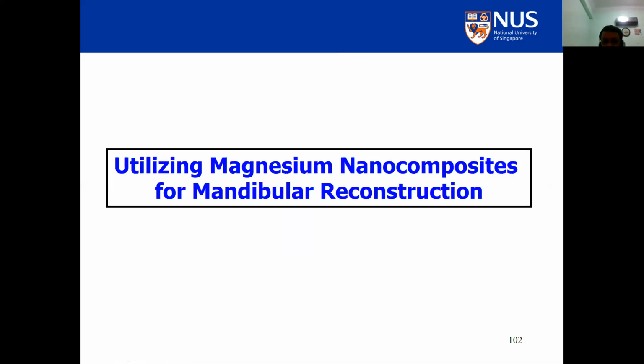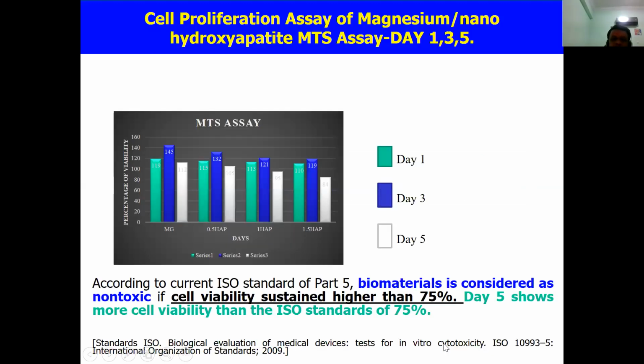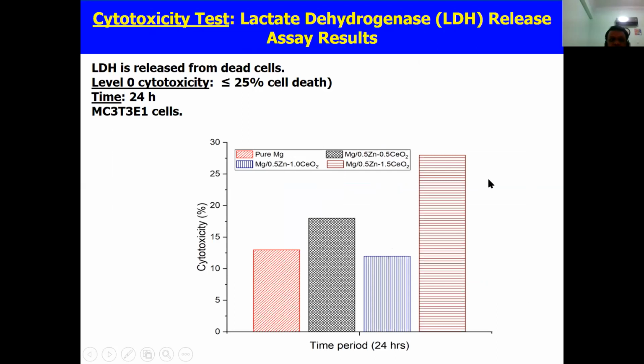So we are actually currently working with the doctors here in the hospital for mandibular reconstruction. We gave some of the nanocomposite to them, magnesium with nanohydroxyapatite, and they checked the cell viability. It has to be more than 75%. So all our material passed based on their test. Then they also did one more test, which is called the LDH test, and it has to show zero or mild toxicity. So all our material, including pure magnesium, of course, are less than 25%. Only the one with 1.5 cerium oxide is 27.5%, but it is acceptable because it's only in the mild zone.